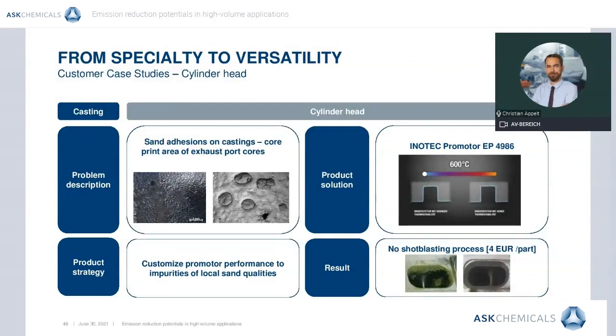In this case, ASK is able to fine-tune the performance properties of the Inotec promoter to the local sand quality used. As the components of both silica sand and the promoter are of inorganic nature, an interaction is commonly observable and changes the properties of the sand core, for example thermal stability. Thermal stability is described as the resistance of a sand core towards thermal and mechanical strain of the casting process, and is an intrinsic property of the binder system itself, characterized by the so-called softening temperature.